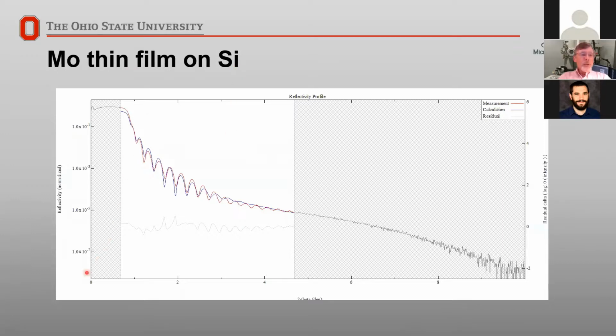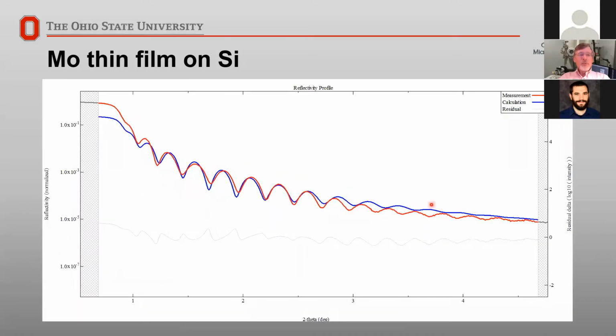So you see here we start at 0 degrees and we went out to 10 degrees. We're only looking out to about 5. So I'm going to be fitting this area in the light, and as I start fitting it, and I look at this fit, I say, you know, that really isn't very good. It sure doesn't match up very well here, and it sure doesn't match up there. What's wrong? Well, as it turns out, we neglected the oxides.